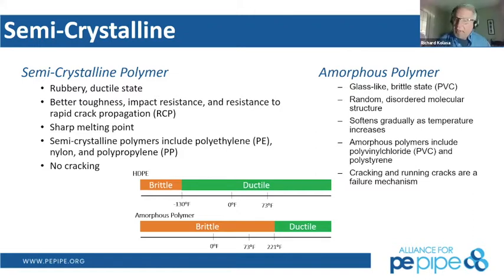So when polyethylene does become colder, it has a higher resistance to impact-type failures and cracking because of the improvements we've made to the joining of those long chains. It has a very sharp melting point. It gets to a certain temperature, absorbs heat, absorbs heat, absorbs heat, and then all of a sudden it can't hold that heat anymore, so it releases it. That's about 135 degrees Celsius. So it's very sharp, and it'll go from a molten state to a solid state and vice versa. It's really important to understand that these new PE 4710 technologies have really stopped the cracking process. And that's a real key.